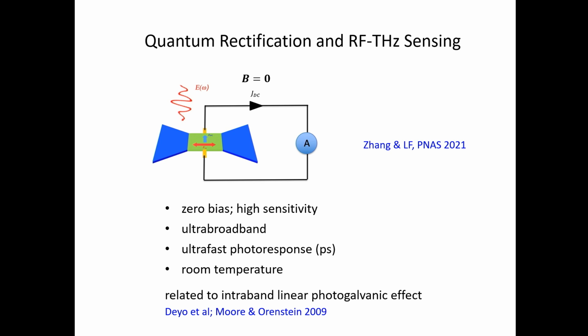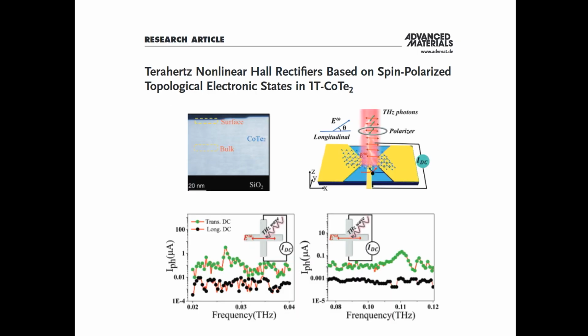Okay, so now another interesting direction is to go beyond these low frequency transport measurements. Because this effect is intrinsic and does not rely on any junctions, it should be able to survive even at very high frequency, even in the terahertz regime. So we propose that if you take a nonlinear Hall material and shine microwaves or terahertz radiation, then it develops a transverse voltage that can be measured. This is a way for RF and terahertz sensing. Because of the rectification effect, high frequency radiation will be able to generate a DC voltage, DC current in the transverse direction. So this, in principle, does not require external power, and it can have very high sensitivity. It also works in a very broad frequency range. Because it's all electronic, its response can be very fast, and finally, it can even work at room temperature. So this could have interesting applications.